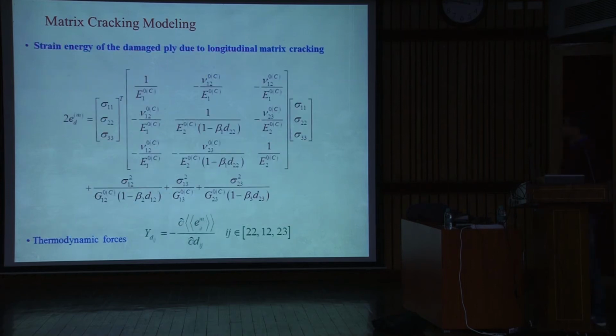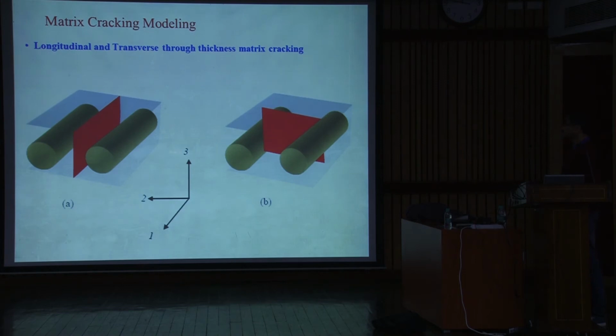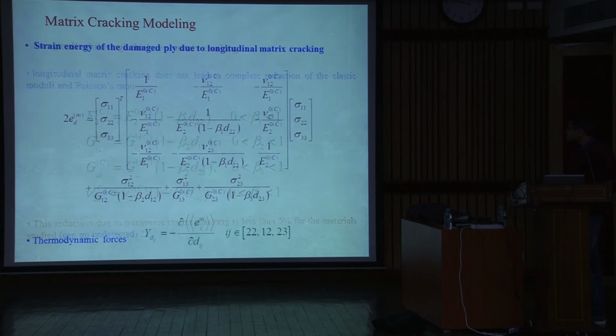So if I consider that matrix cracking, then what is going to happen? Sorry, I will go back. So this one is going to affect your stiffness in the longitudinal direction, the fiber direction, and then in the shear directions. So my stiffness in the longitudinal direction, the perpendicular direction to the fiber in this plane, and in the shear is going to be affected. Now you see that it is affecting your stiffness in two directions and the shear. For this strain energy, you can again get the associated thermodynamic forces for these damage variables.